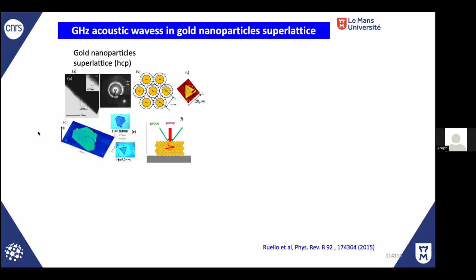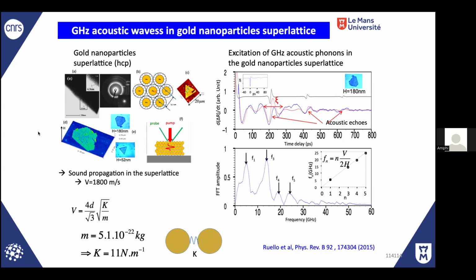We just have these 4 nanometer particles, but in the situation where we have 2D materials, you have just a layer. On the surface, you have such a bond stiffness that connects the 2D material to the substrate. And you can induce vibration of that 2D material, and then you come back to this van der Waals interaction, like you just induce mechanical oscillation of the layer. So that works quite well. The main issue is that if you have a 2D material and the substrate has a thermal conduction which is too low, then you burn the sample. But okay, just heat management. But the idea is really that situation.